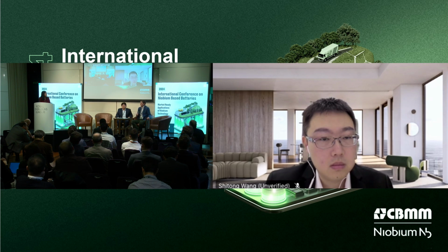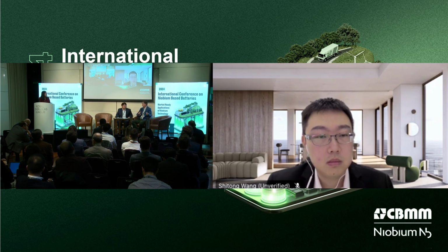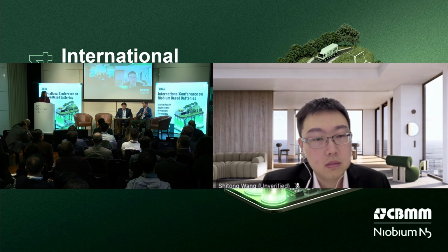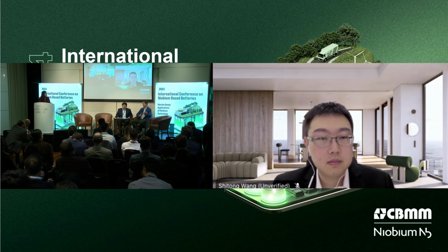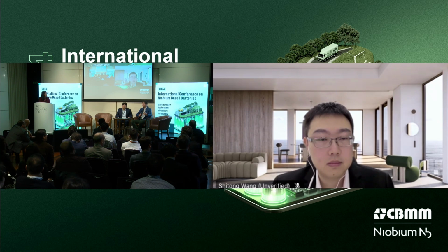If I understand the question, I think there's a good chance that the difference between LTO and NTO, if you're not adding any conductive additive or binder, and you're looking at the materials as a function of, say, lithiation, is that it's actually the microstructure that's affecting it. Because LTO is a zero volume expansion material, you're maintaining whatever grain boundary contacts you had originally. With the other materials, even 5% volume expansion will be dominated by these grain boundary effects. So you're not really looking at intraparticle transport, you're looking at interparticle transport.